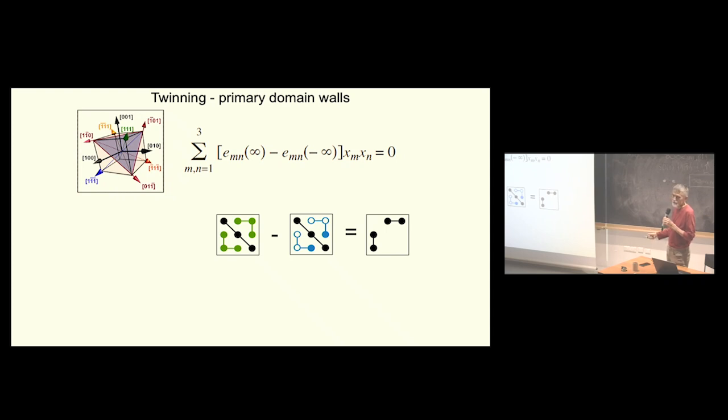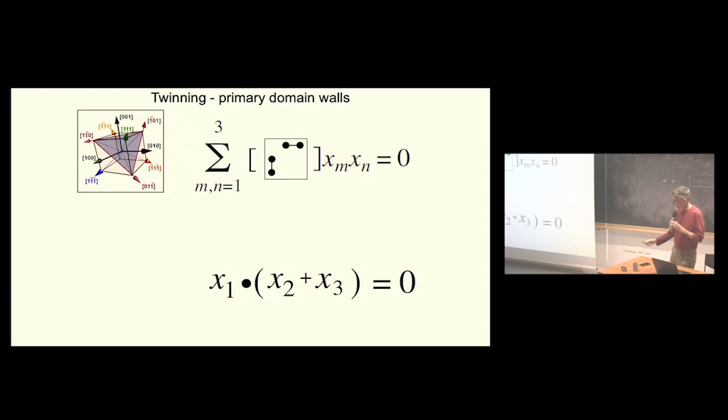So this is the difference graphically, whatever the numbers in the matrix are. Then if you think about the solution of this equation, there is some number, and because it's symmetric, the number doesn't matter, so I can divide by it. I can divide by the full dot product, if you wish, and I get just this sort of equation. It tells you that one mirror which is mechanically compatible is perpendicular to x1, and the other is just given by this normal vector.